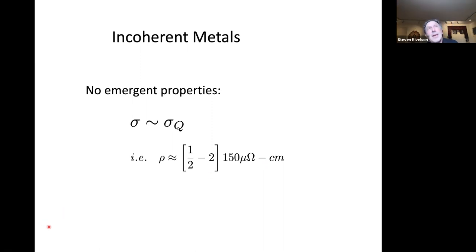My prediction is that anything that doesn't have a reason to have something else is going to have a resistance in the range between a half to 2 × 150 micro-ohm centimeters, right? That's my theory of incoherent metals. And it's not going to be strongly temperature dependent because the only energy scale in the problem is the Fermi energy. So I expect that it will be this value and it won't depend very strongly on temperature.